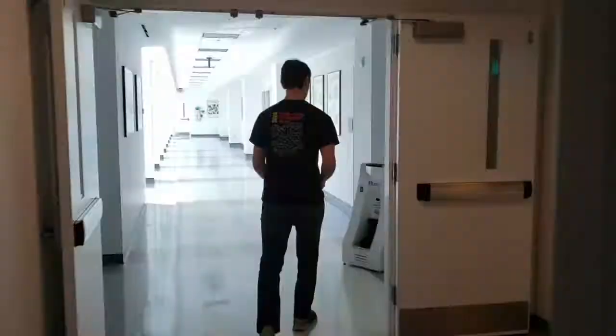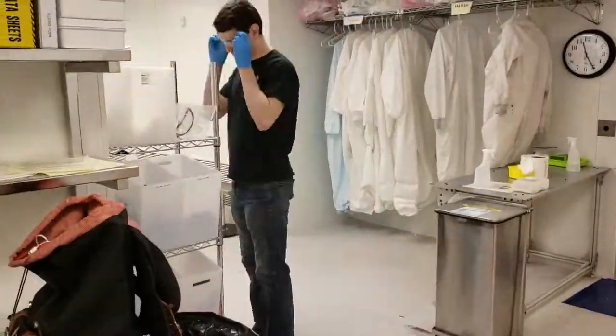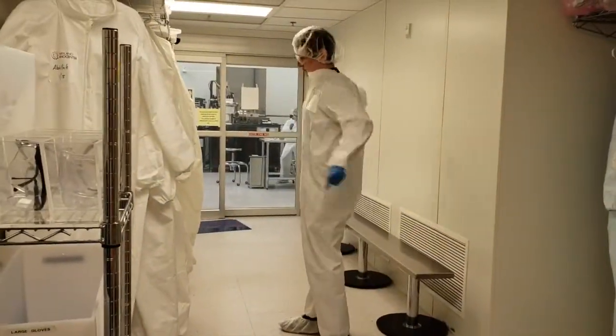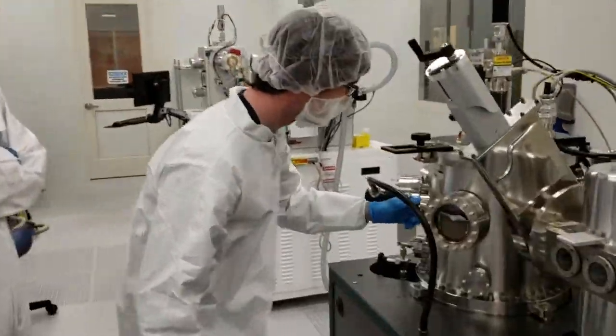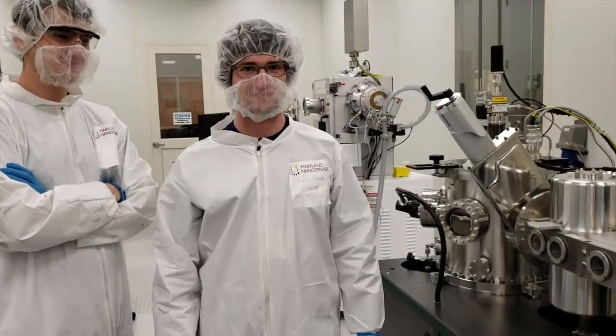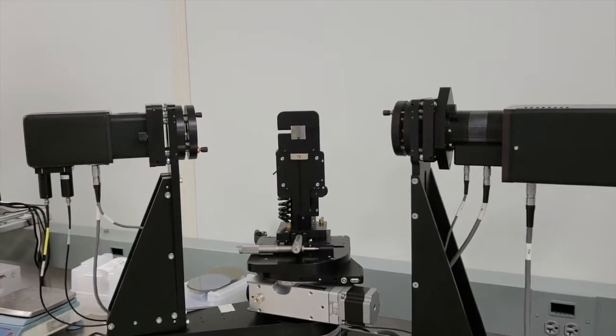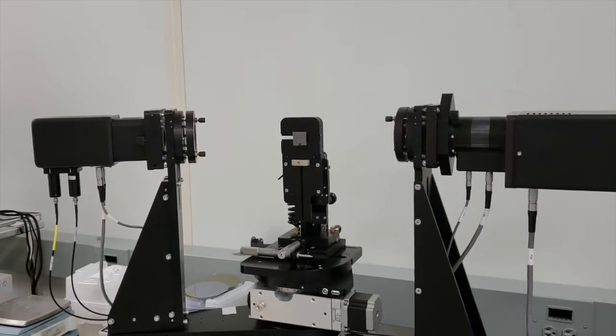Once we determined the composition of the alloy from DFT, we went to the Fab Lab to make it. We co-sputtered the silver and copper alloys on glass slides using the sputtering system in the UMD Fab Lab. By varying the power ratio between the copper and silver targets, we controlled the composition of the resulting alloy. We deposited several alloys with varied power ratios and analyzed their optical properties, composition, and uniformity using ellipsometry, XPS, and AFM. We decided that when we fabricate our solar cell, the best way to do this would be upside down, because it would allow us to keep the interfaces in our device smooth.